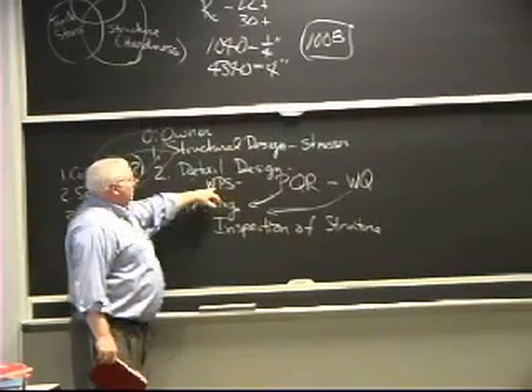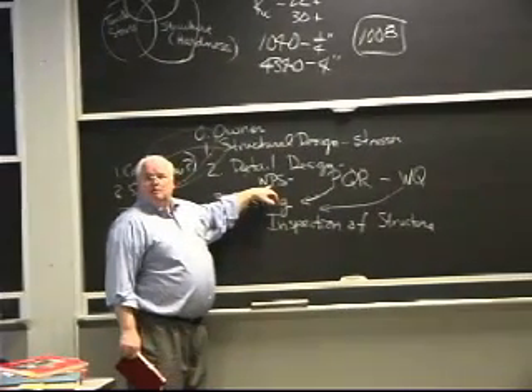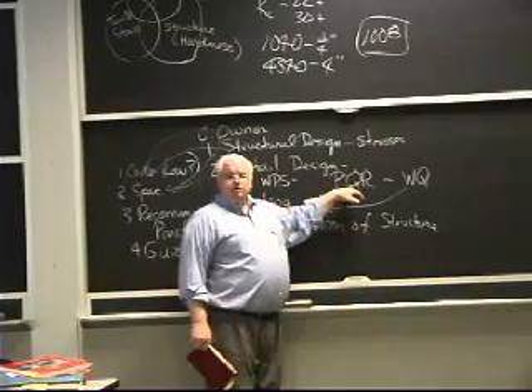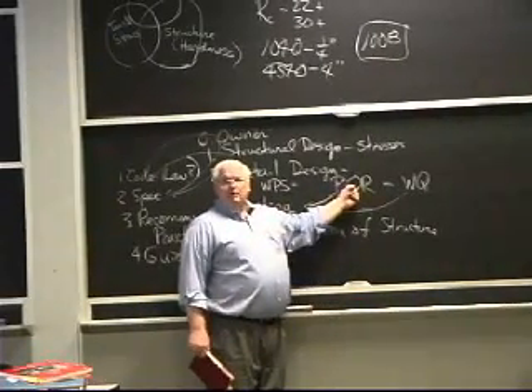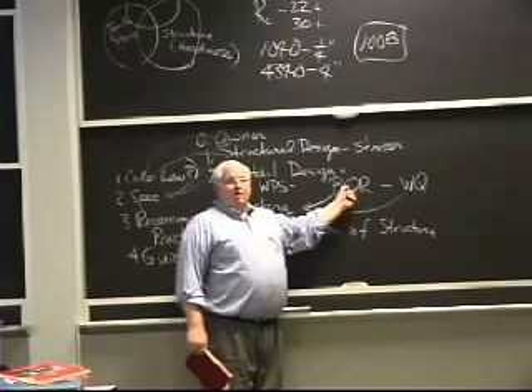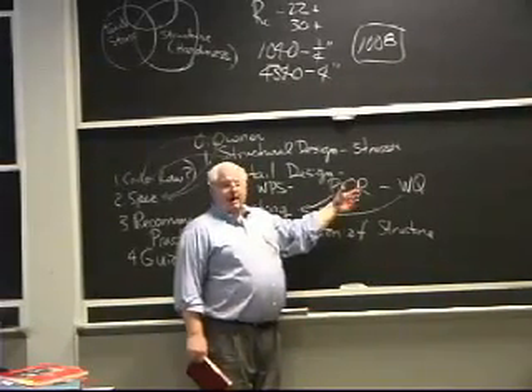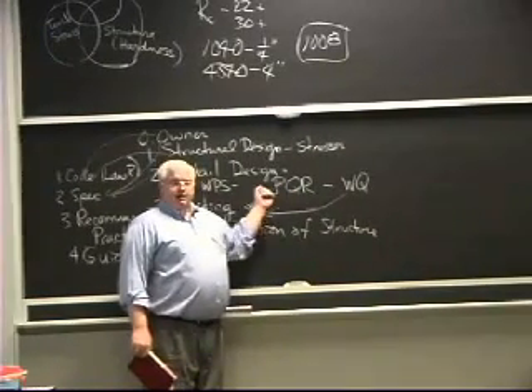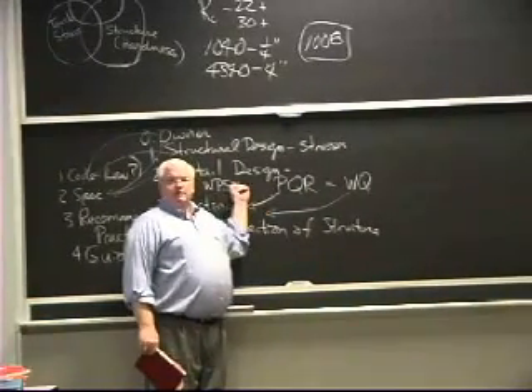And this welding procedure can be 1 page, or it could be 10 pages long, depending on how complex the recipe is. Procedure qualification records are typically a couple of pages. You actually weld the plate, send it out to the test lab, hopefully pass the test, radiography, bend test, make sure you don't have any cracks, a whole host of tests, okay? If it passes, then you have a qualified procedure. Then you have to have the welder prove that he can make the thing.